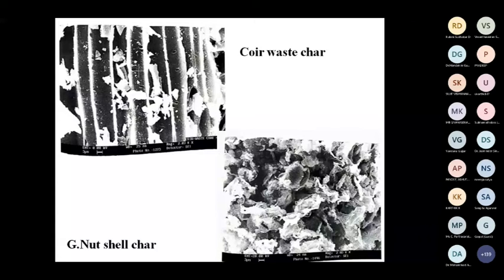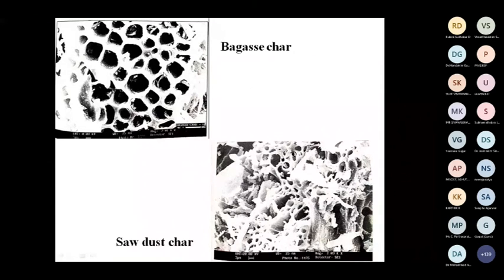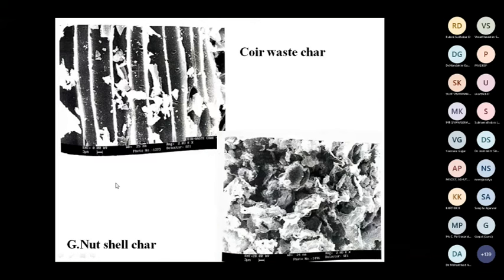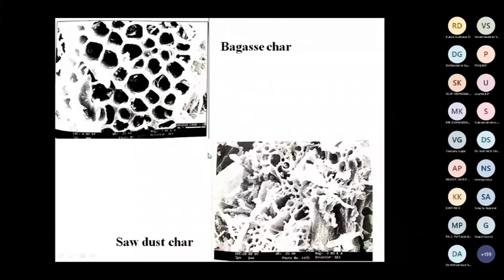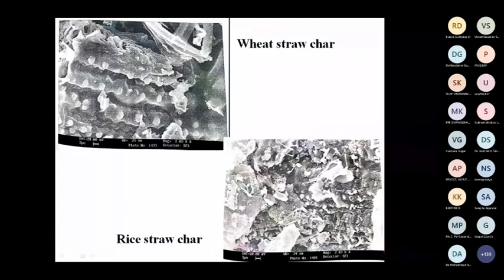All the chars are. See the bagasse, you can see a lot of pores. Similar for sawdust. So these fuels, bagasse, sawdust, and coir waste, have a highly porous structure, and a lot of surface area is available. That is why now you can explain and confirm that the DSC profiles' second peak is more intense than the first peak because of the highly porous structure. The entire surface is available for heat release with respect to coir waste, bagasse, and sawdust. If you consider wheat, straw, and rice, these are not highly porous. Rice is also not highly porous.